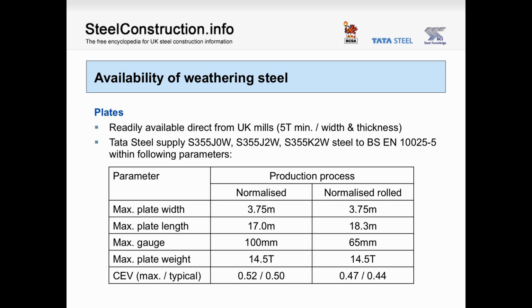Now the last row in the table is CEV, which is carbon equivalent value. This is effectively a measure of the alloy content in the material. The higher the number, the slightly more difficult it is to weld. So Tata Steel developed a low CEV version of weathering steel that you can see on the right, and that's produced through the normalised rolled process route up to 65 mm. It can also be produced through the normalised route up to 100 mm thick.